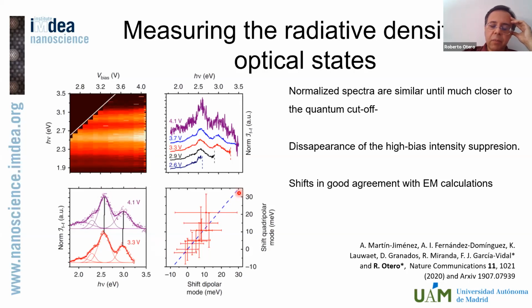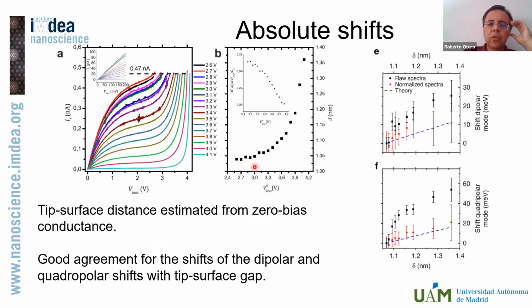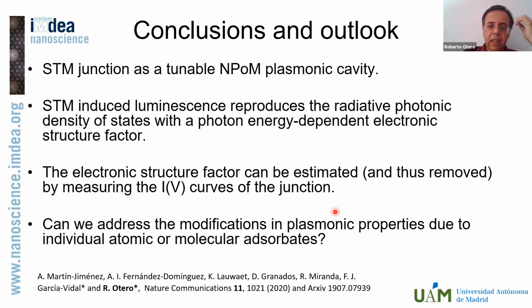And what I'm doing here is comparing the shift of the low energy mode with the shift of the high energy mode. I'm doing that because in principle, it's difficult for me to know what the actual tunneling distance is. But if I make an effort to analyze this distance by measuring the zero bias slopes of the IV curves, I can plot the shifts in the low energy and high energy peaks as a function of the tip surface distance. And you can see how after normalizing the spectra, they correspond pretty well with theory, whereas they wouldn't before.